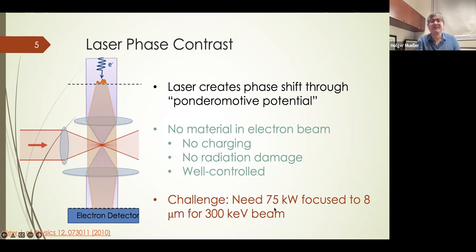The problem is we need 75,000 watts of laser radiation focused to 8 microns to make a phase shift for a 300 kilovolt electron beam. Picture that. 75,000 watts is a lot of power, right? And it's focused to 8 microns. So what we're talking about here is the brightest laser focus that has ever been made anywhere with a continuous laser. This isn't easy, okay? Pulse lasers can reach these intensities fairly easily, but usual electron microscopes are continuous, so we need a continuous laser.